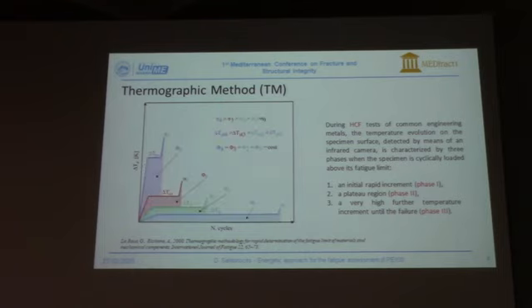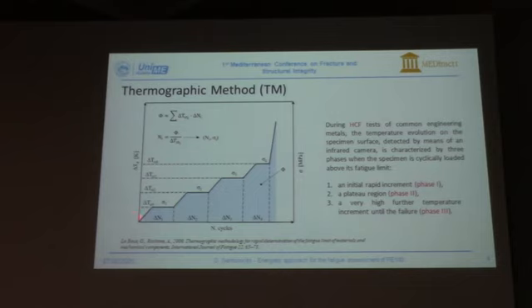So generally, the higher the stress, the higher the stabilization temperature, but on the other hand, we can assume the energetic parameter constant. So if we apply fatigue cycles in a stepwise way, and we obtain the different stabilization temperatures, and we can calculate the energetic parameter, we are able to obtain the number of cycles to failure at which the material will break if cyclically loaded at that stress ratio.